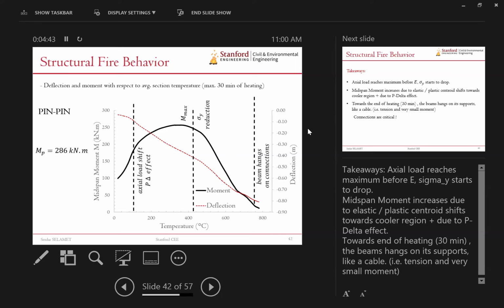And then when we get reduction after 400 degrees in yield stress, obviously the moment starts to drop, and then almost to zero when we have the beam hanging at the supports. If you look at the plastic moment capacity at ambient, you can see that it's actually very close to the plastic moment capacity of the beam before it starts to reduce, and that's why we get this reduction, because it's almost at its capacity in terms of plastic moment.